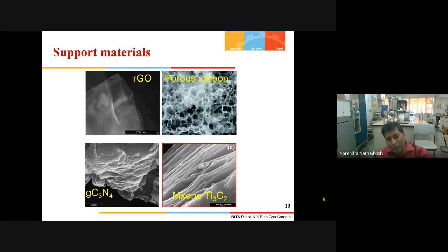However, when we are talking about graphitic carbon nitride and MXene, one of the challenges is that the layered structures sometimes collapse during the catalytic reaction or electrochemical reactions. When they collapse, the available active surface area becomes reduced. So we have to adopt some strategy so that their collapse is prevented.